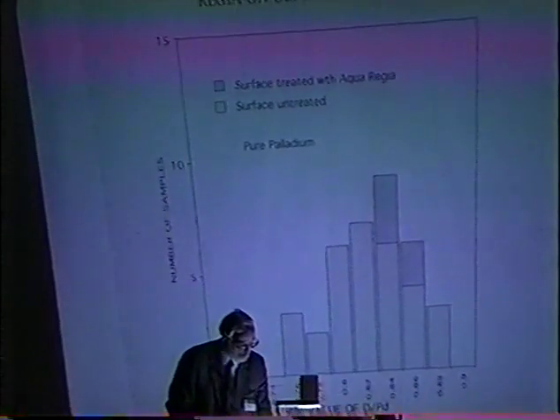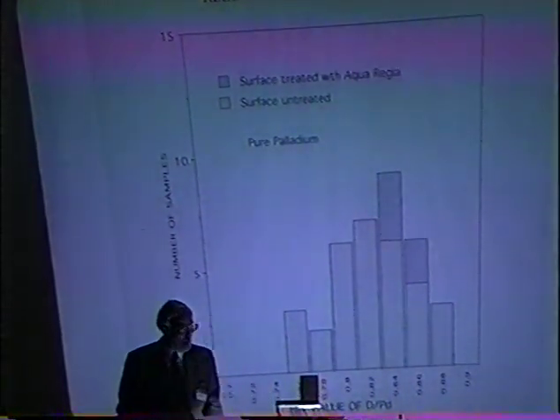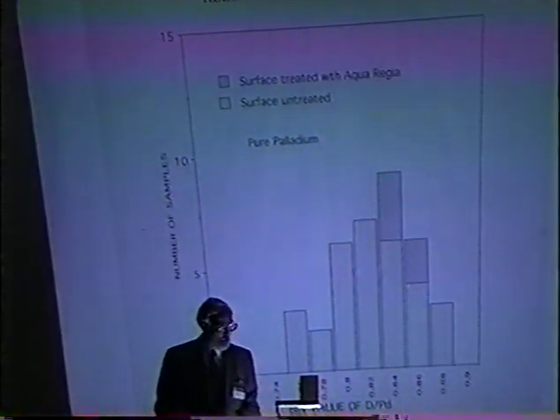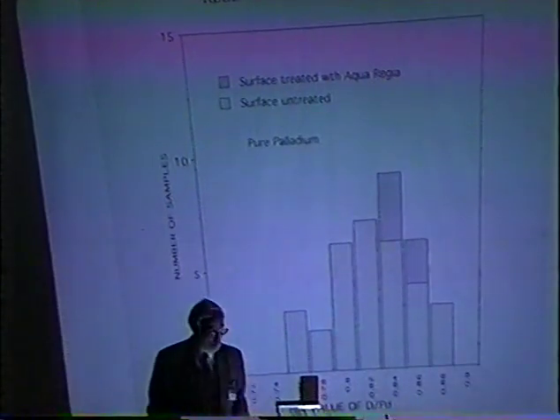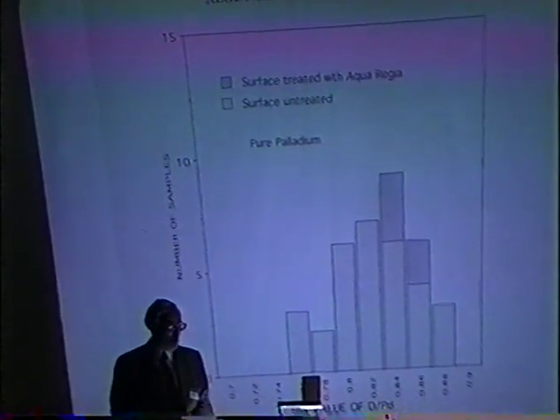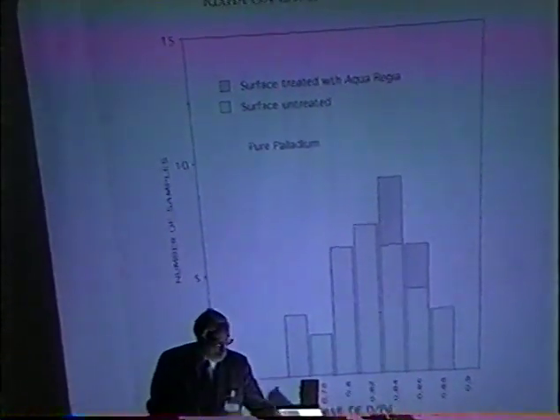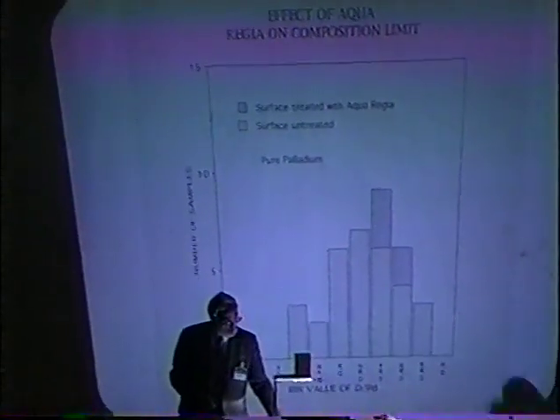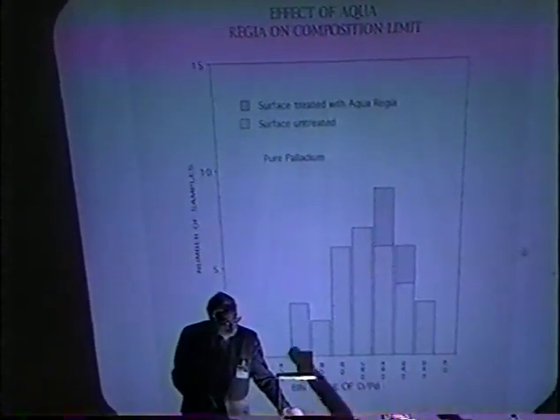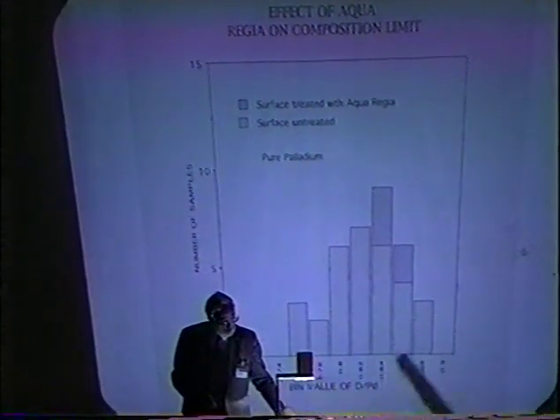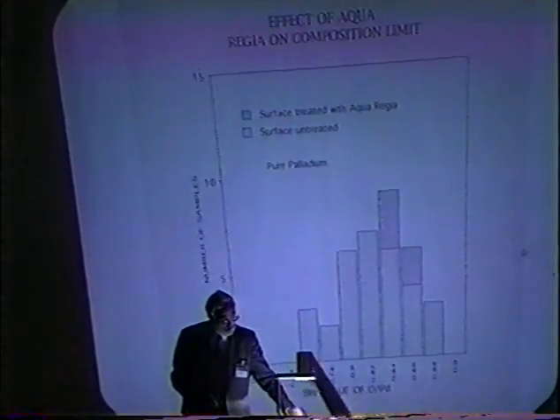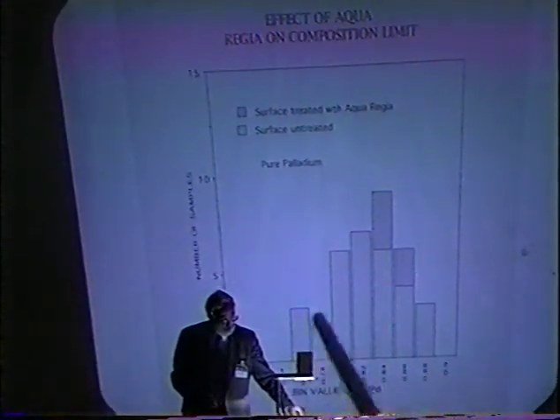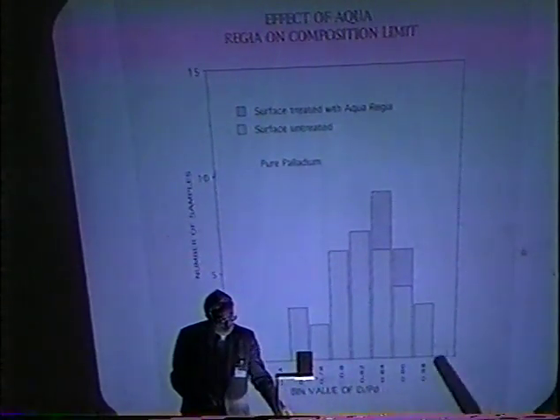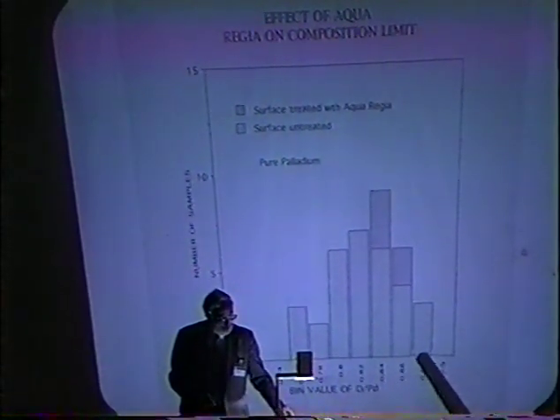If you compare the loading behavior in terms of a histogram, you get a characteristic behavior that is applicable to almost any property. There'll be a range of values. This is pure palladium, and you can see that for no apparent reason, the loading went from 0.76 up to about 0.85.